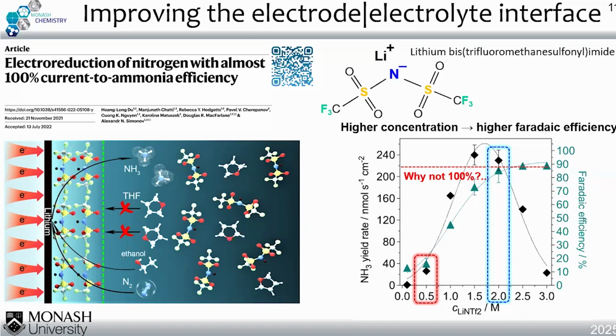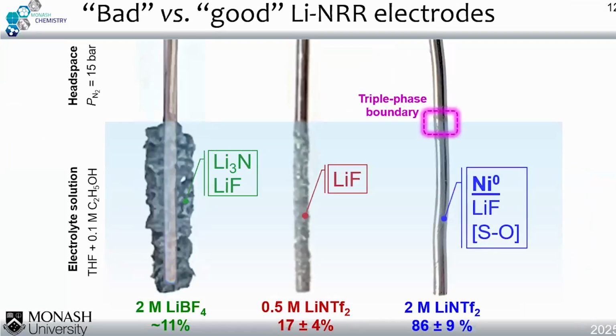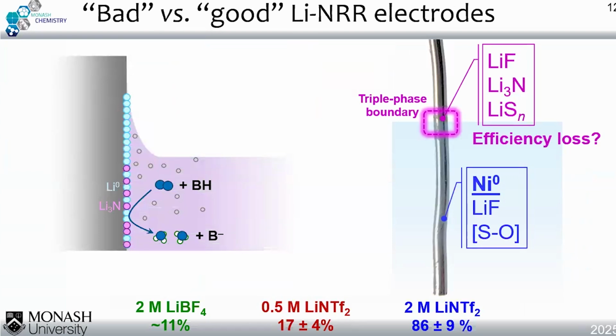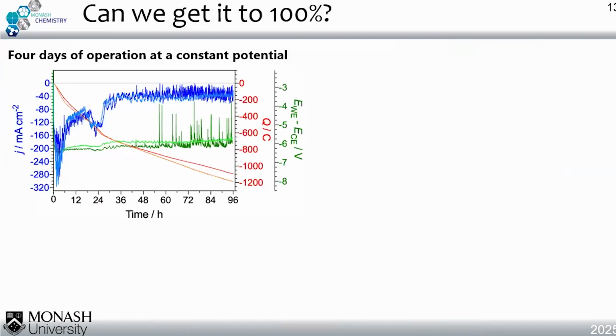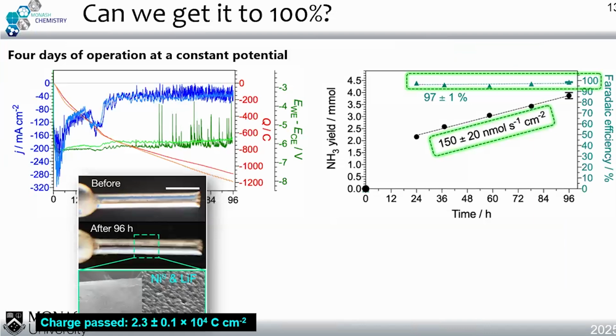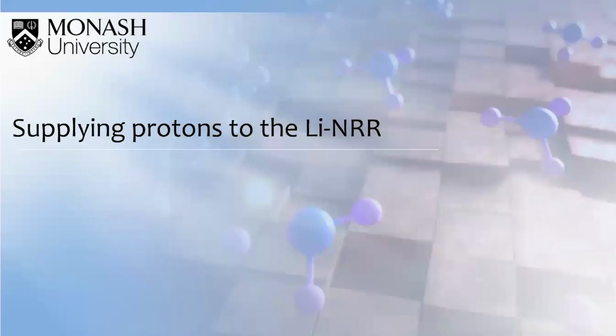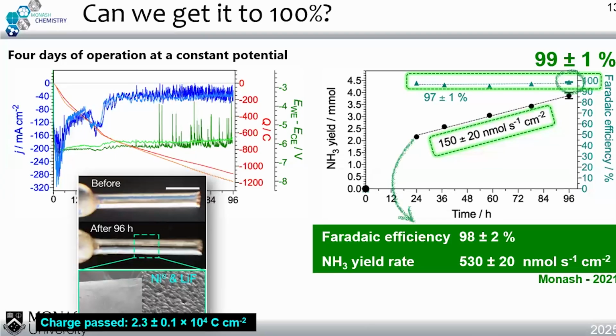Therefore, we started to explore more on the surface, and we found a region called the triple phase boundary. The triple phase boundary is the region that has a mix of solid, liquid, and gas phases, and that actually causes a lot of side products like lithium fluoride, unreacted lithium nitride, and even lithium polysulfide. So we fixed the problem. We resolved the triple phase boundary, and we can extend our performance up to 4 days, with a record-breaking passed charge of 2.3 times 10 to the power of 4 coulombs in 2021. And most importantly, we can achieve Faradaic efficiency of almost 100%, with a maximum rate of 530 nanomoles per second per cm squared as well.